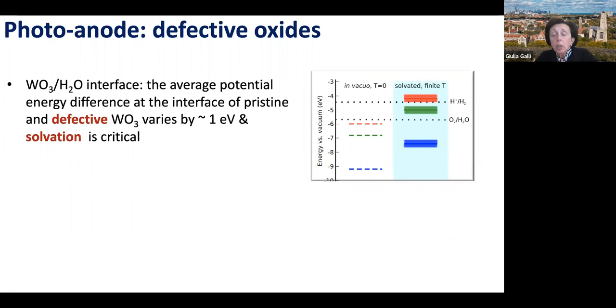And already here you kind of see that the overpotential is going to be substantial. It doesn't tell you the number, but gives you an idea that this valence band is not too close to the oxygen level. This is an important quantity to get, right? Because it's what tells you whether that oxide is good or not. Exactly.